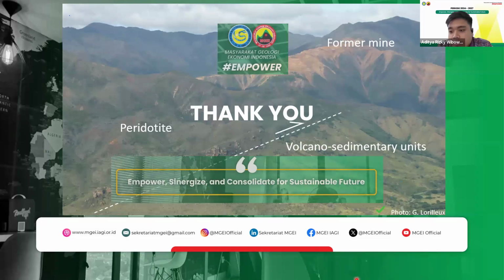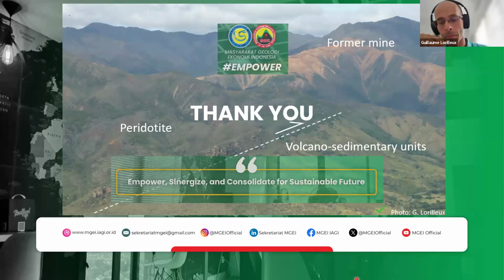Based on the chart presented, does saprolite appear to be less dense than limonite? Yes. The density, the bulk density, is actually lowest in this transition zone. But as soon as compaction starts in the limonite, we start to progressively increase the density.